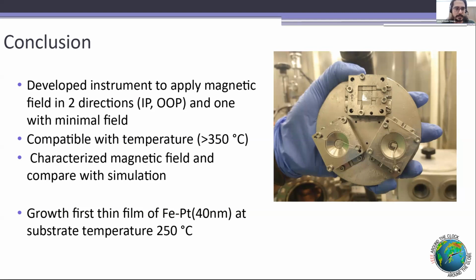But the biggest conclusion that we can have is that the instrument could apply two different magnetic field directions, and one with minimum field, all together in the same sputtering round. And it's also interesting because it's a modular setup, so you can change the module according to your interest. If you want two in-plane or two out-of-plane, we can move it. And it's compatible with temperature. The characterization of the magnetic fields was comparable with the simulations that we had. And we successfully grew a first round of thin films with it.